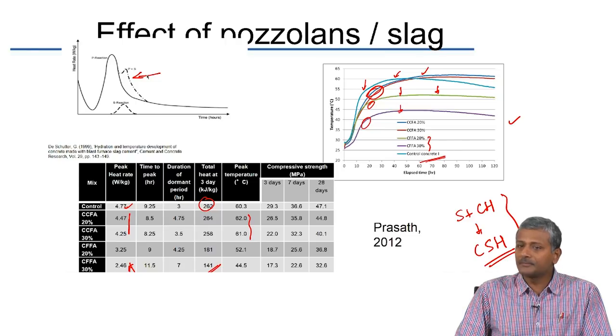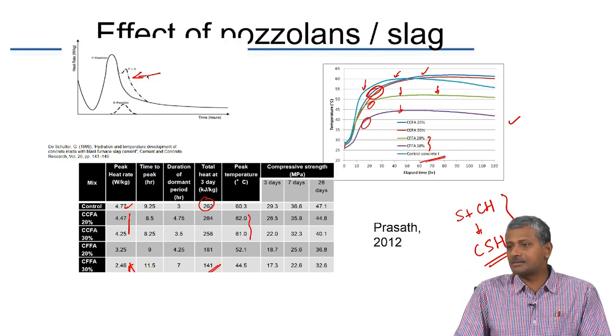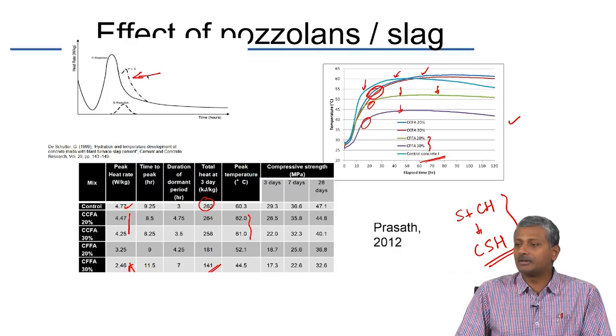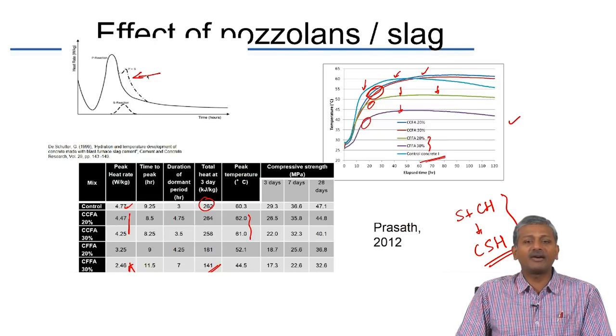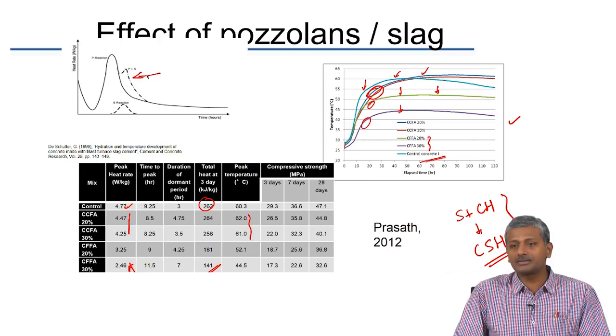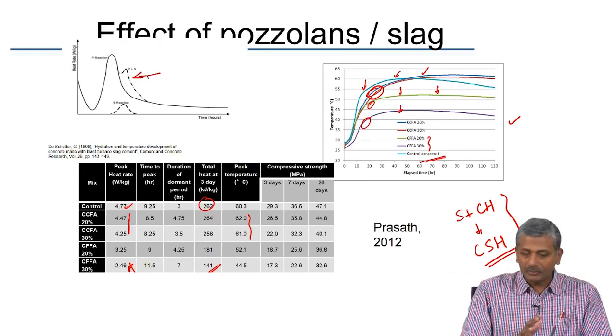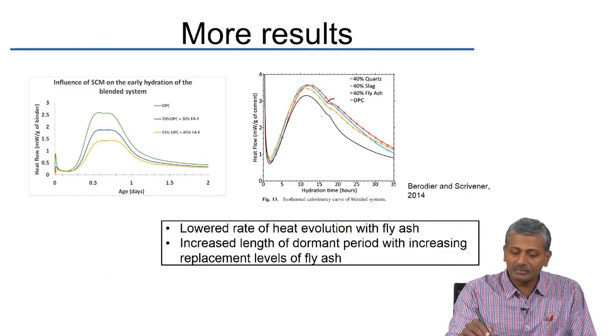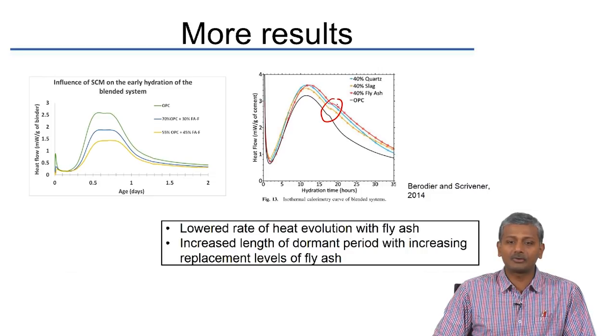Slag contains the same oxides as cement: calcium oxide, silicon dioxide, aluminum oxide, and iron oxide. There are combined phases such as calcium silicate and magnesium silicate that are not as reactive. Very finely graded silica particles in slag can be reactive and produce a high heat peak early in hydration. In some cases, an additional peak — barely discernible as a hump — can be observed in heat evolution patterns comparing different cement blending materials.